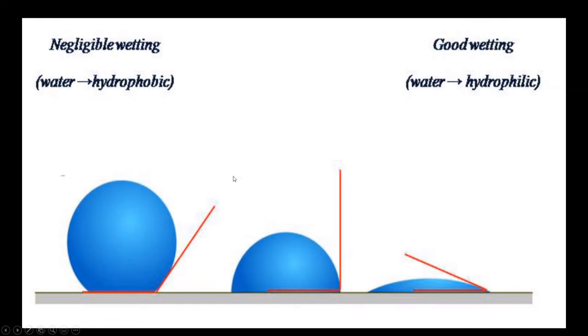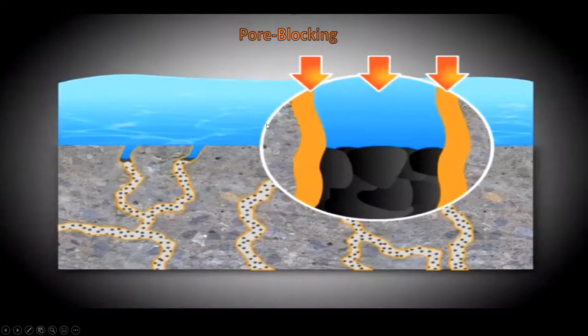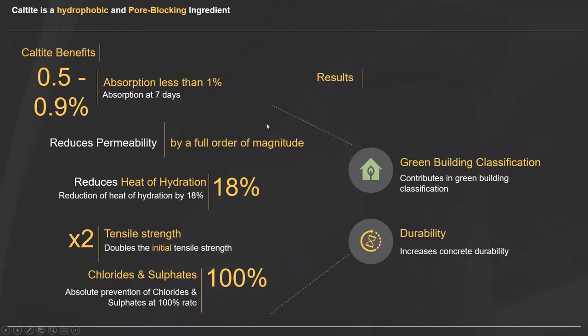So that's the hydrophobic component. I'm sure you're aware of contact angle and how that affects wetting and drying. And the pore blocking one, as we just explained. The additional benefits of using this HPI concrete, apart from the fact that it's obviously water repellent, if you look at a pretty standard test, the BS 1881 part 123 absorption test, this is usually done at 7 days rather than 28 days, according to our specification anyway, so that if you've got any problems or any potential problems, you identify it very quickly after the structure has been built. Very typically, the specification calls for less than 1% absorption in 7 days, and very typically you'll get between 0.5 and 0.9.